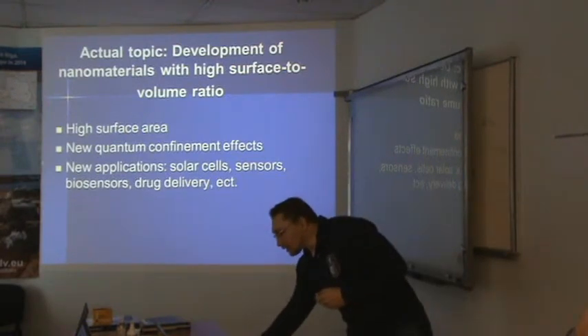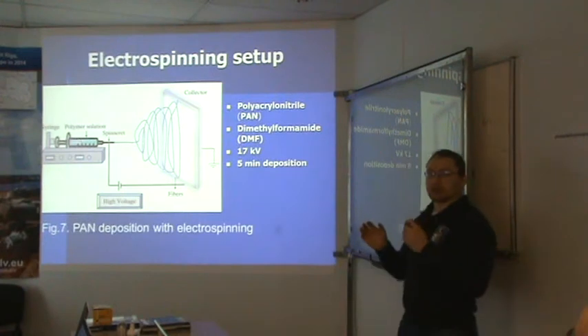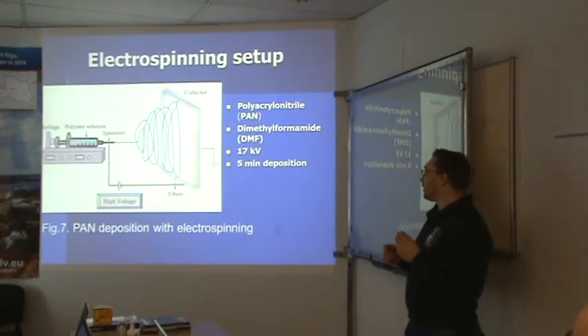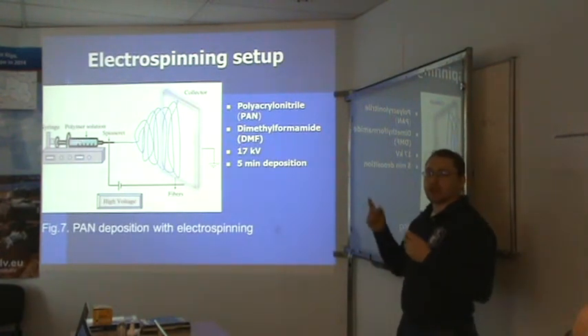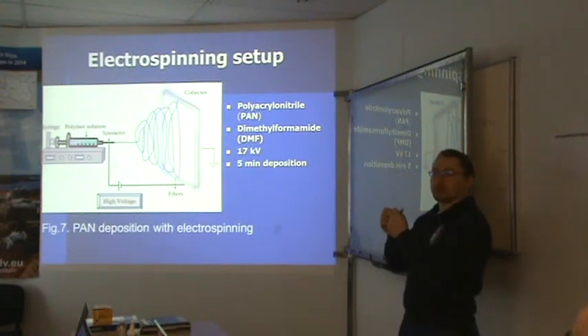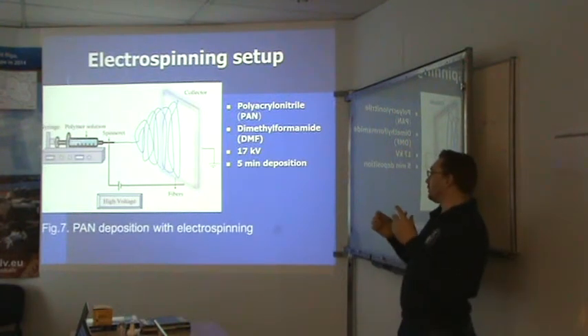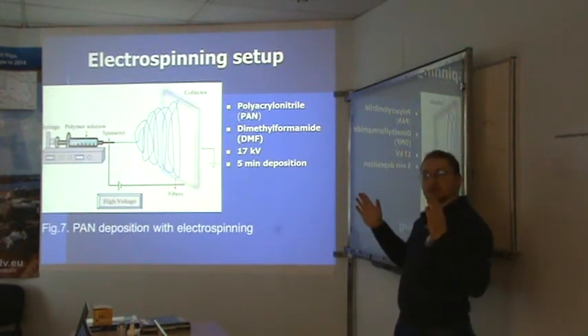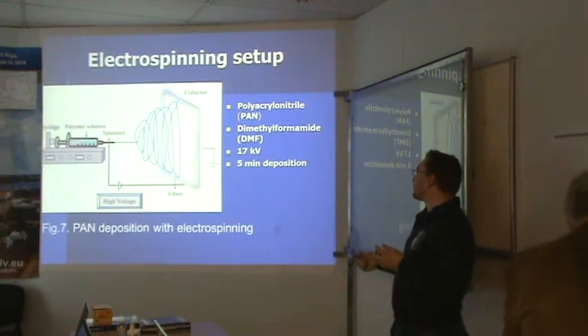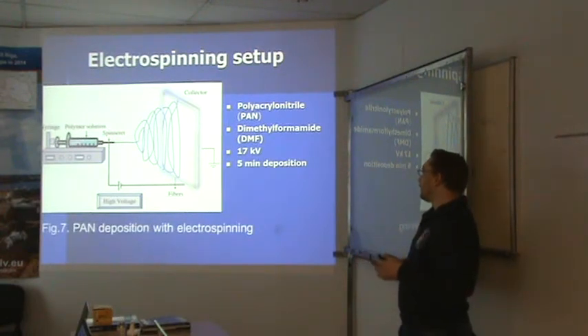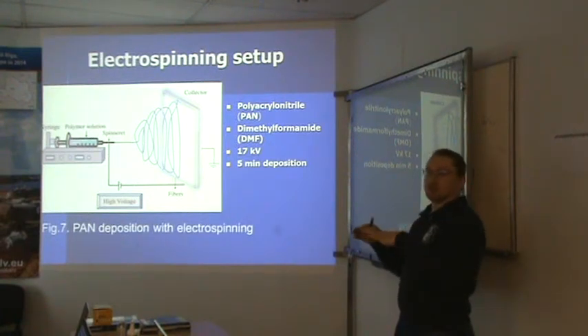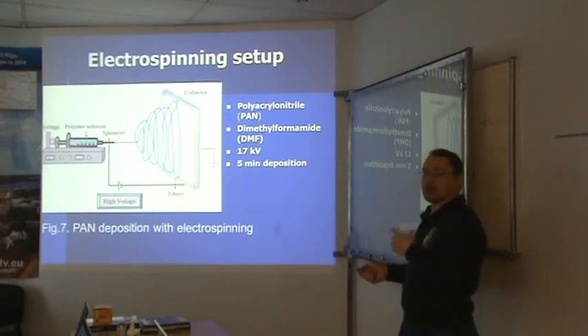In this case, we combine two technologies: the electrospinning technique, which produces organic nanowires. You mix a polymer solution with organic polymer, and you use an electric field to create these nanowire structures. And then you put these nanowire structures inside the reactor, and you coat all of this nanowire with thin layers of zinc oxide and nanolaminates.